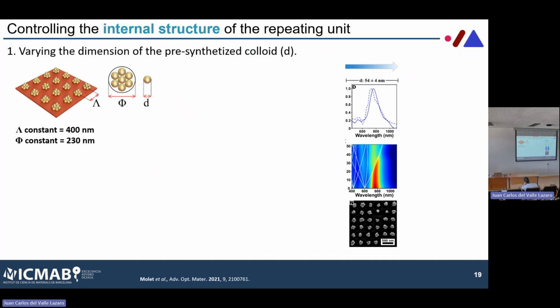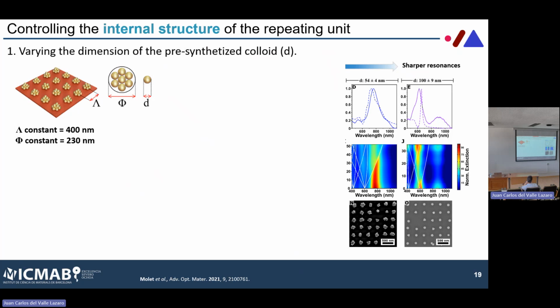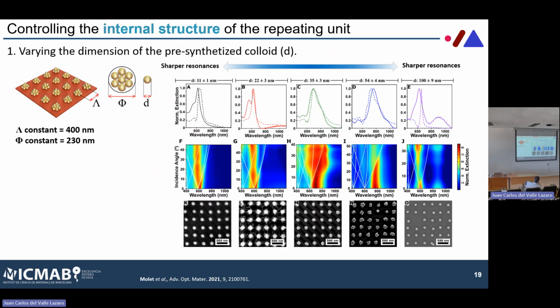The first thing that we came up with was, okay, let's change the composition of the repeating unit. And so in this work, what we did was change the dimension. The idea was that the problem is that the near-field coupling within every single cluster makes my resonances so broad and increases the optical losses of the system, so that I'm not able to bring down the optical losses and see my sharp lattice resonance. So let's make the particle bigger so that my cluster will ideally be made of single particles. And this worked to a certain extent, but templated self-assembly is not extremely good at positioning single nano objects. As you can see here, the lattice is not very precise, and this ended up losing the quality of my optical delocalized response.